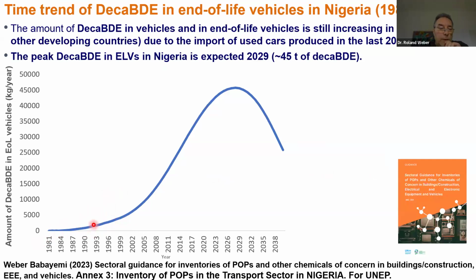And what you see here is the amount of DecaBDE in end-of-life vehicles. So what you see here, we are now at 2020. It is estimated that in this year, we have around 35 tons of DecaBDE coming out from this total 1,000 tons, which we still have in use. But this amount is still increasing until around 2030. In 2029, we estimate that about 45 tons of